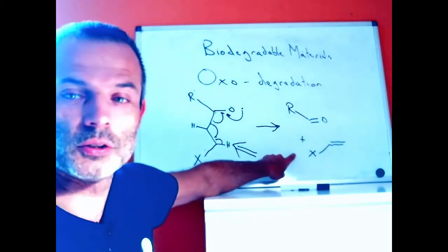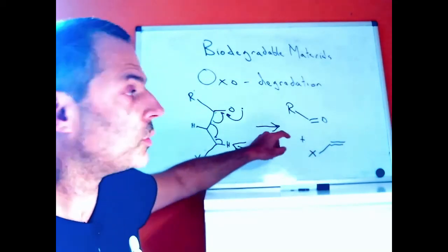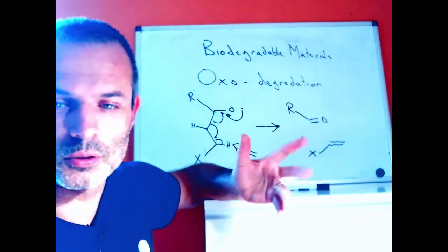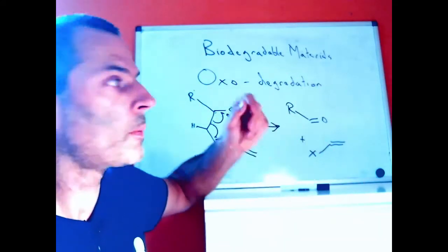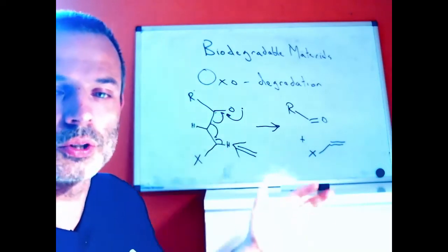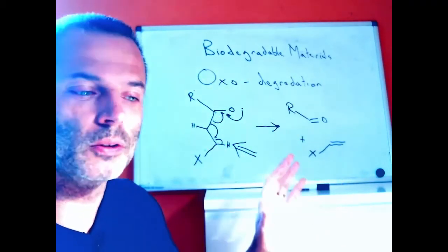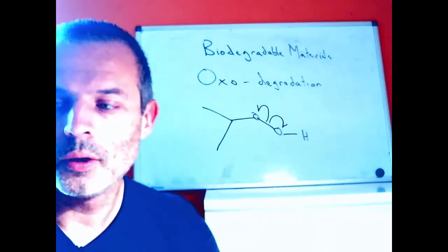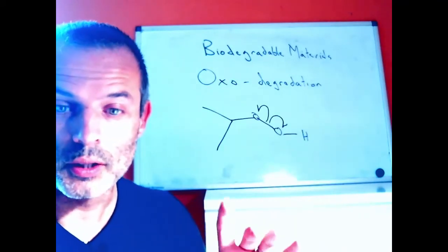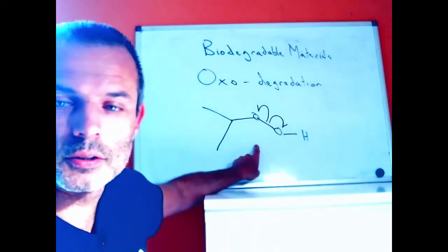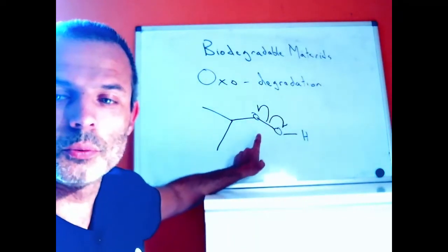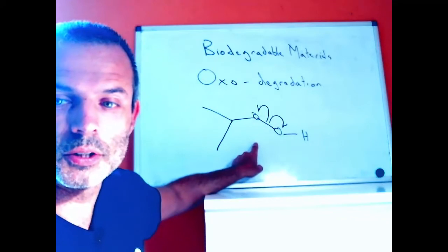That's these small sections of polymer, particularly the ones with the double bonds on. They become a sort of liquid. So we go first of all to higher molecular weight, and then we go to lower molecular weight, which is typical for polymer degradation. What we established is that this step is the rate determining step, and so we need to know how we can influence it.